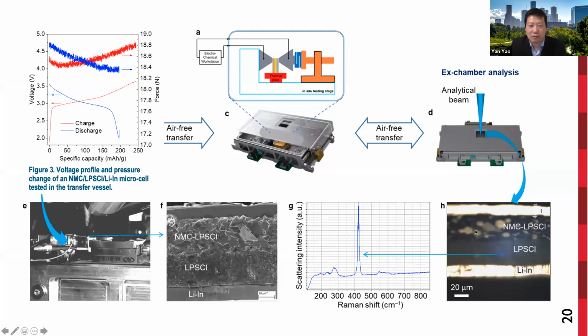So that test platform has also been optimized to deliver performance similar to non-micro cells. The first discharge capacity reached 200 milliamp hours per gram, which is comparable to that of thin cells. So the pressure change can also be monitored in situ. So these results indicate the efficacy of the vessel in isolating the test platform from ambient conditions without interfering with any analytical beams.